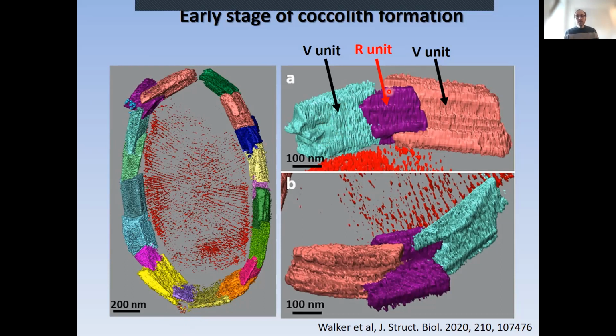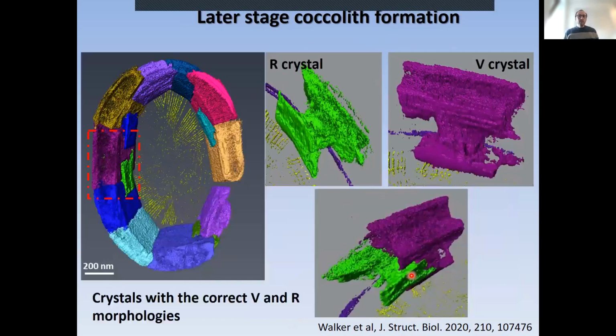They are mechanically interlocked. They're not fully formed yet because you can see that the units in green and this kind of pink color still have to grow more upwards and form this kind of anvil-like structure. And the one in the middle, it's starting to grow the coccolith from the back. And this is the late stage. It's all almost mature. And we have these coccoliths here that already have the morphologies, the V and R unit, and